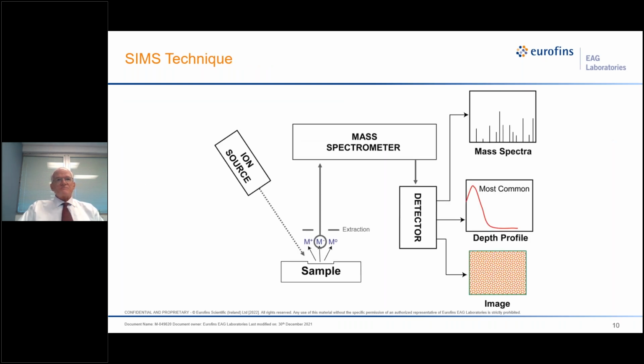Here's how it works. We have an ion source on the left, which bombards the sample and erodes the sample, so the instantaneous surface from which the particles are emitted recedes into the bulk as the analysis proceeds. And the sputtering will cause positive ions, negative ions, and neutral atoms to be ejected. And I want to stress that by far and away, most of the particles that are ejected are neutral, and they are unavailable to us because it's a mass spectrometric technique. We have to have ions. So then the ions are passed into a mass spectrometer and into a detector.